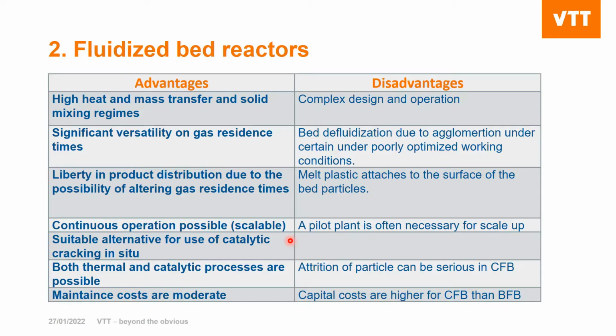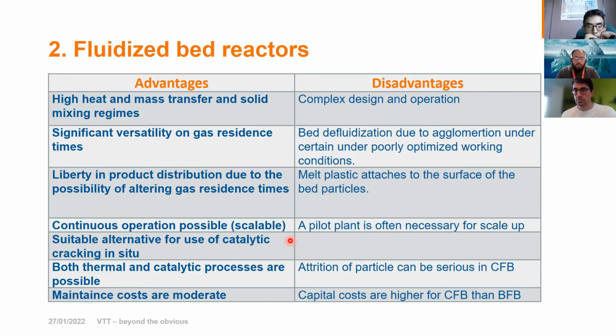So basically what it means is that if you, for instance, have bigger particles of plastics going into the bed, and the residence time is not enough, they can melt on the surface of, for instance, sand or any inert material, and this will defluidize the bed. They will form agglomerates, which means that it's not fluidizing anymore. So the bed will go into the defluidization mode. In the other case, if the velocity of your fluidization gas is not optimized, which means that it's not enough for the bed to fluidize, your bed will also be in the defluidization mode. So that's possible, depending on the operational parameters.